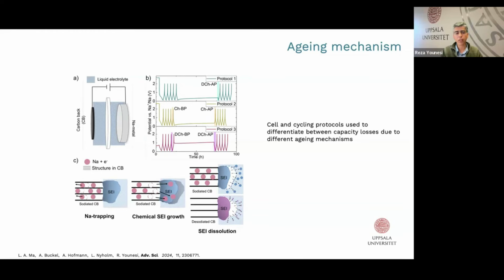On the second protocol, for example, after the pause we try to take sodium out from the working electrode. And again, by measuring the amount of charge before and after pause, we can understand if SEI was exposed to any of the aging mechanisms and if this dissolution happened.